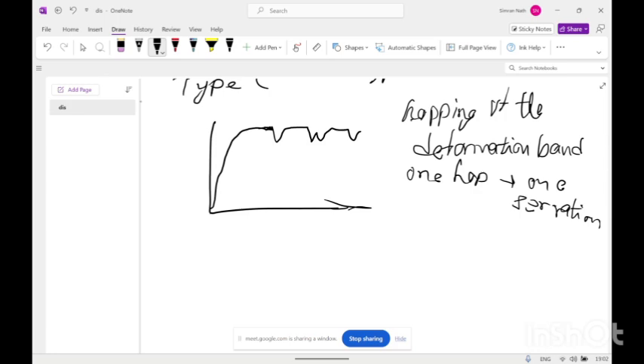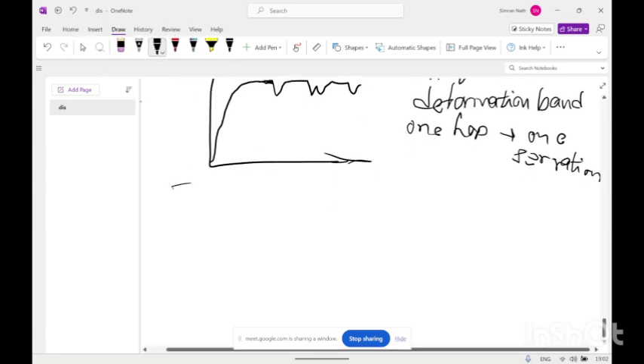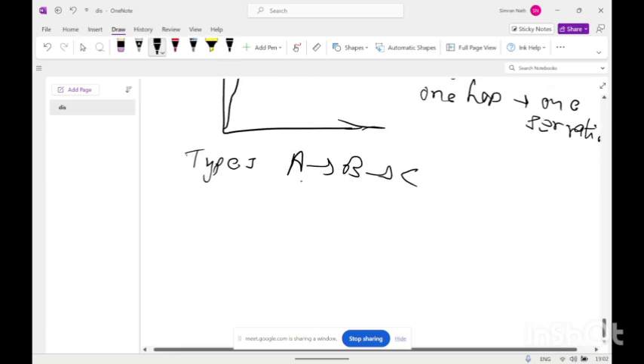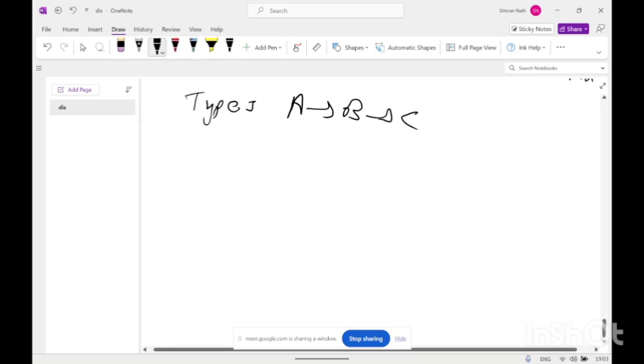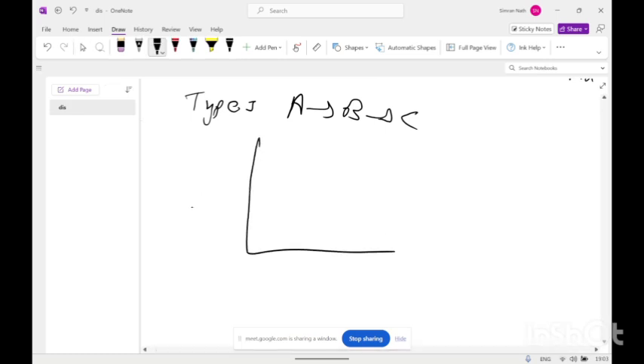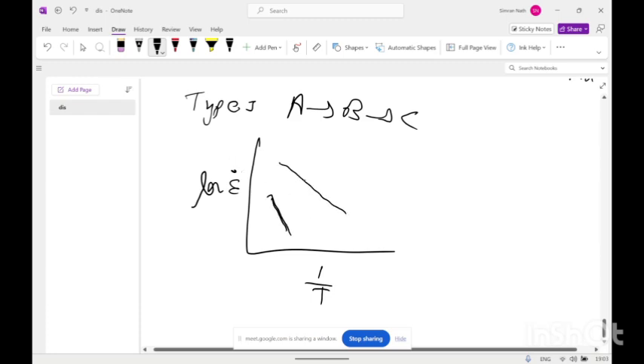So the change in the deformation band types is from A to B and C. So in the initiation of the deformation, first A type of serrated flow is found, then it changes to B, then C type. If we plot the diagram of log of strain rate versus 1 by T, between these lines the shifting in type of serrated flow is from, like, this point is A, this is B, and this is C. So out of these two lines there will be no DSA.